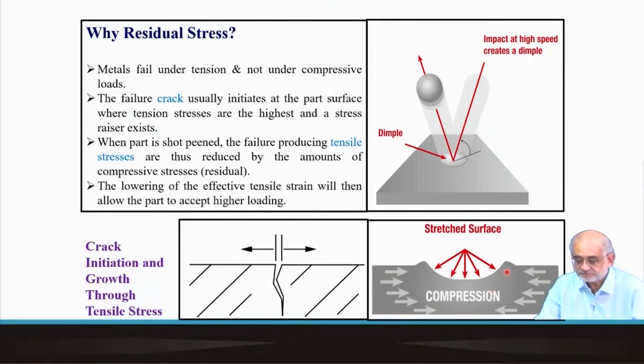so that we are able to develop the desired level of stresses. So for a single event, if we magnify, we can imagine that this is the deformation region, and as we deform, there will be a tendency for the deformed metal to flow out and form these ridges. But this doesn't happen unless the diameter of the ball is very large. But in this particular case, as the material tries to deform, it tries to push the grains away from this point of contact. And there's a limit up to which the material can flow laterally away from the point of contact. And when it can no longer push the grains beyond, then from that neutral plane, after the impact is over, the region around will try to push the material back into its original form. And that's typically the nature that we expect for material having both elastic and plastic deformation characteristics.